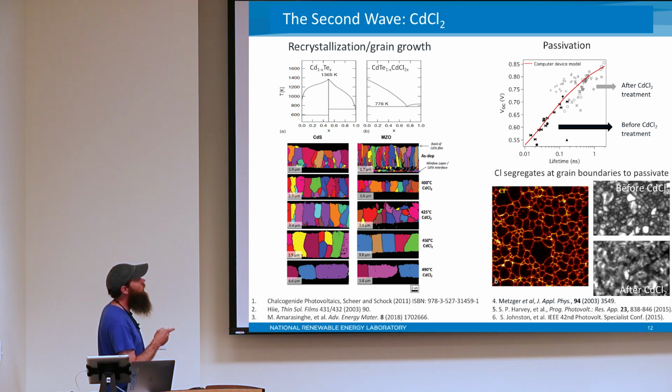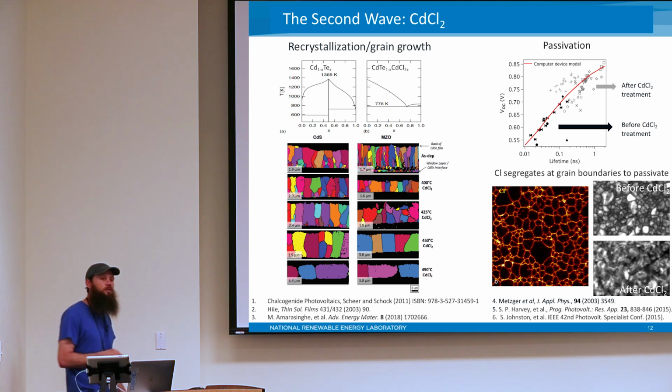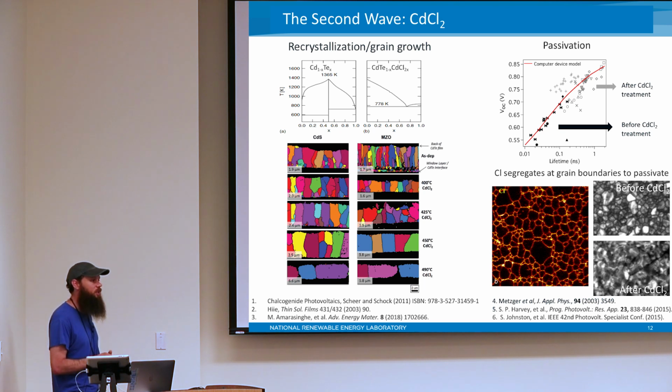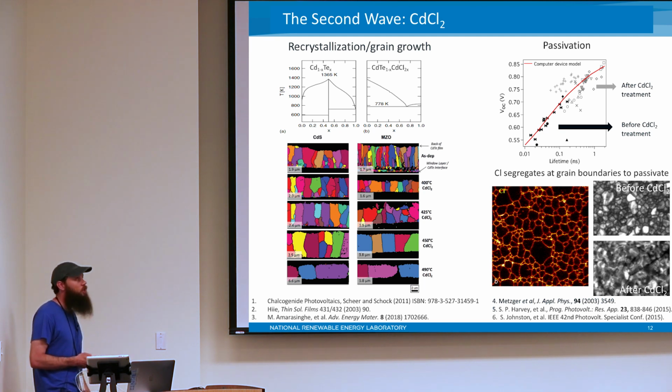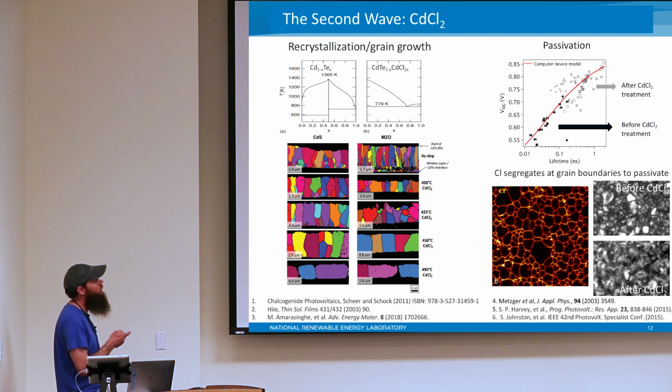However, if you introduce cadmium chloride, you can form a eutectic, which drops that significantly. And if you inject oxygen into it, it actually drops it a little bit further. So going and doing this then allows you to basically dissolve those bad grains and make them better.